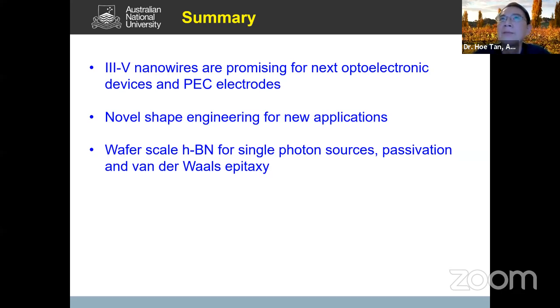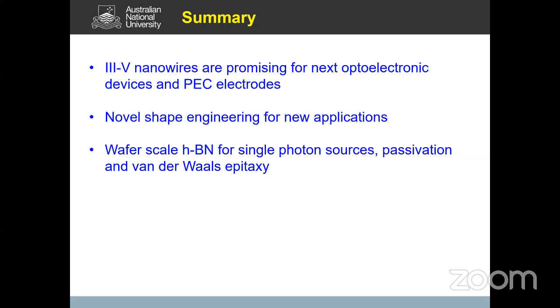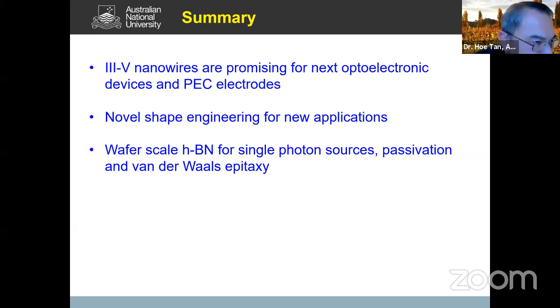Okay, thank you. There is another question. If we use a wide band gap semiconductor like titanium oxide instead of zinc oxide, will it increase the efficiency of indium phosphide nanowire solar cells? Yes. As I showed before, the absorption is still done by the 3-5 material. As you know, 3-5 material is a very good absorbing layer. The highest efficiency solar cell is made of 3-5 materials.